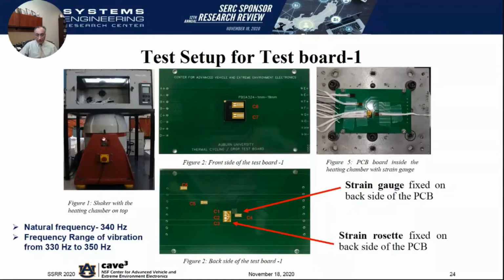The assembly is mounted on an electrodynamic shaker. That's what you see here inside a thermal chamber. We are actually sweeping in a tiny range of 330 to 350 hertz, and that's because the natural frequency of the assembly is 340 hertz. Since we are testing a large number of board assemblies in this program, each one of them is slightly different. Therefore, instead of exciting at a single frequency, we are trying to do it in a narrow range of frequencies to be able to not vary the test protocol from board to board.